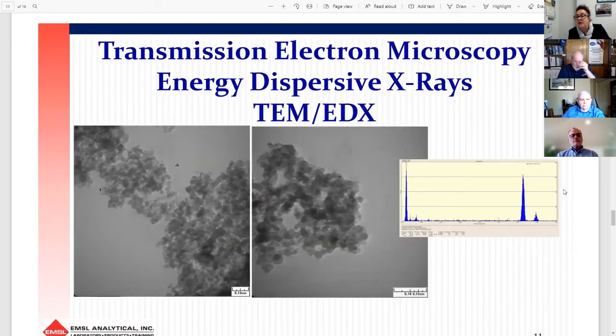And if we look at the size, the individual particles, the little round spheres that you see in the pictures, are about 20 nanometers. So it's a nanoparticle. It tends to agglomerate in this grape-like morphology, which we define scientifically as aciniform, but it has a very definitive, distinct way of presenting itself, and that's how we identify if it's soot or if it's not soot. And if you compare with that image that I showed previously, you can see this type of detail.